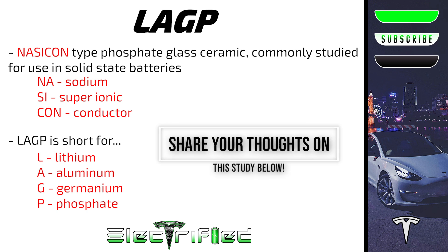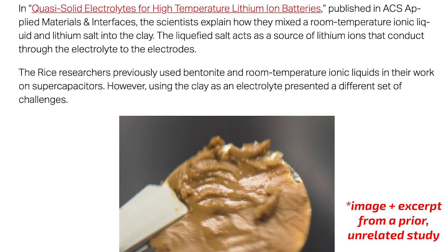With this advancement, a tailored multifunctional interlayer between the solid electrolyte and lithium anode can address these interfacial issues. The interlayer is designed by creating a quasi-solid-state paste in which the functionalities of LAGP and the ionic liquid — denoted as IL — are combined. In a solid-state cell, the LAGP-IL separates the lithium from the LAGP, which creates a chemically stable interface with low resistance and prevents thermal runaway at elevated temperatures. Solid-state cells designed with the interlayer can be operated at higher energy densities while maintaining high levels of safety.